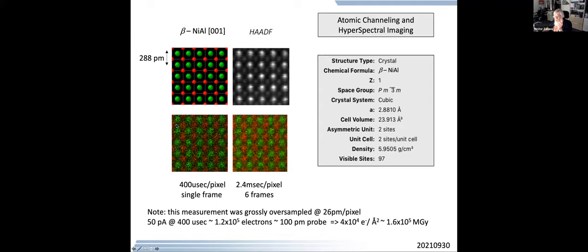But the important thing I want you all to realize is that this would be a typical dose for a hyperspectral image, 50 picoamps at 400 microseconds. That's pretty low dose in terms of material science. But if you convert that, and assuming we have a one angstrom probe, that's a fairly high dose.